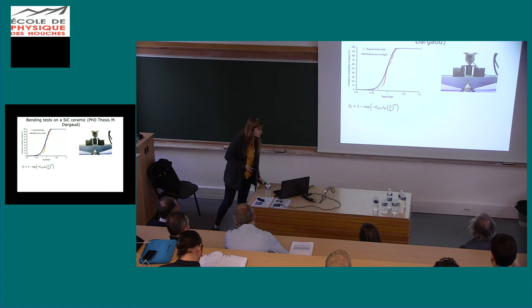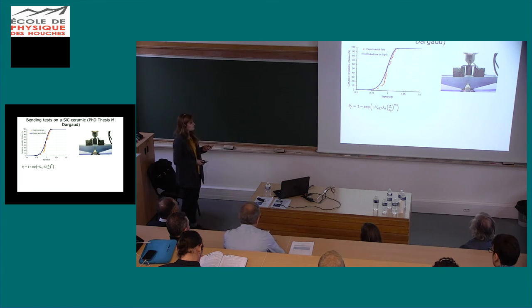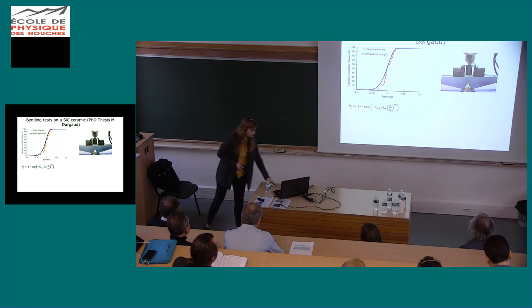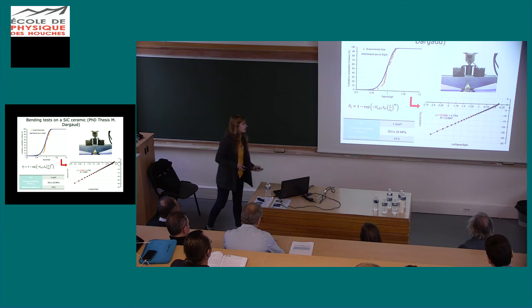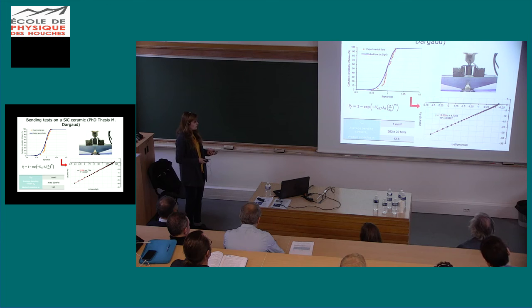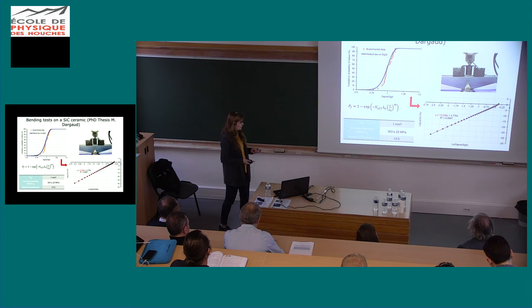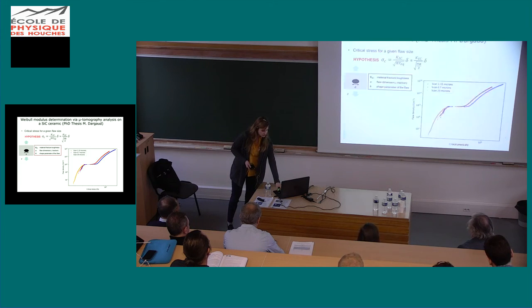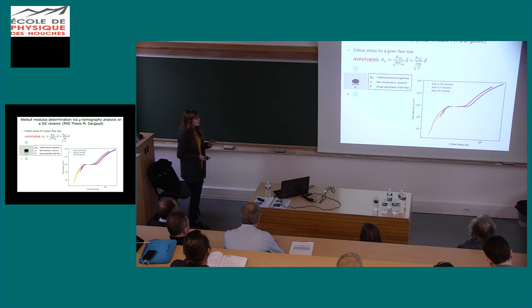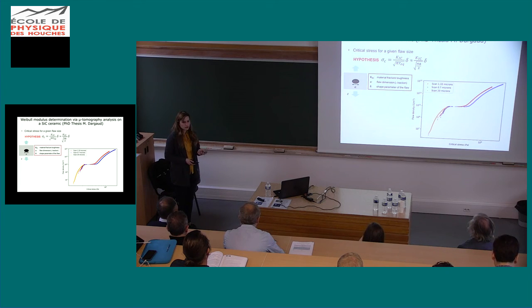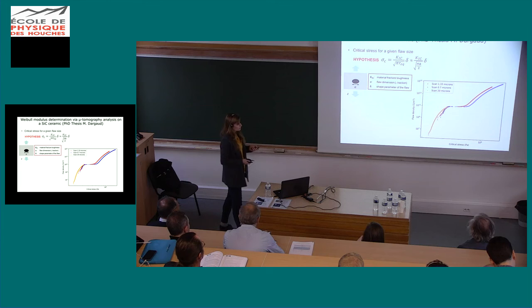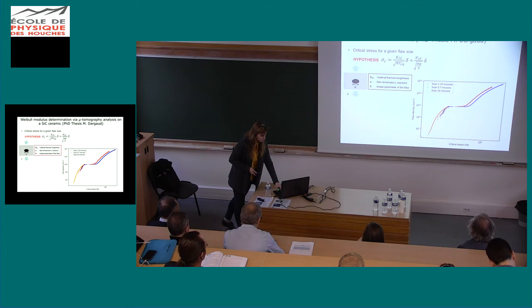On these ceramic samples, we performed a 4-point bending test. So you get this probability of failure that you can fit in order to obtain the Weibull parameters. For this ceramic, we reach this value of average breaking stress, and we have a Weibull modulus around 30. By taking the same hypothesis, we can link the size of the defect to a stress of activation under tensile loading. Here we still have the plot for, let's say, 3 different resolutions of scans.